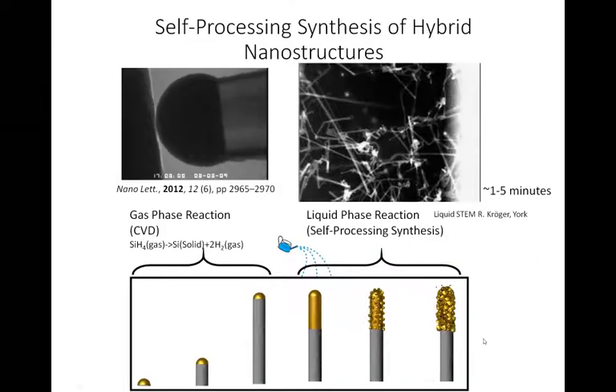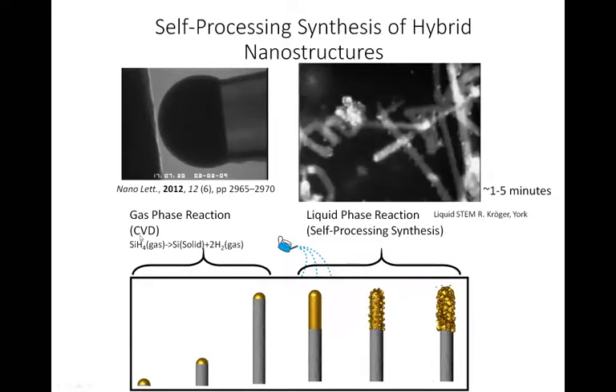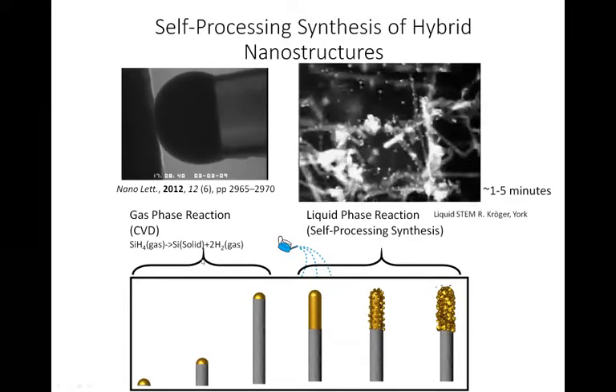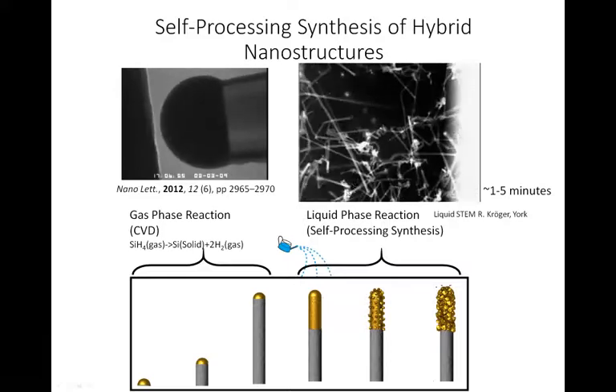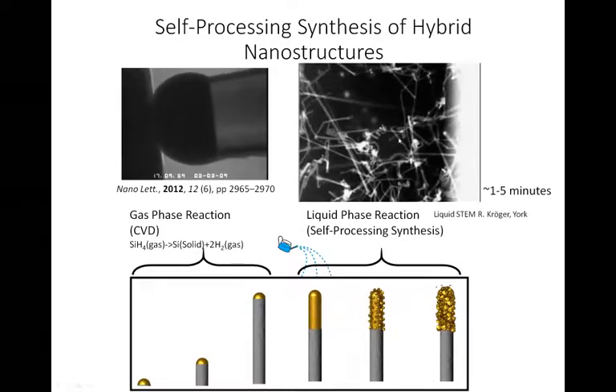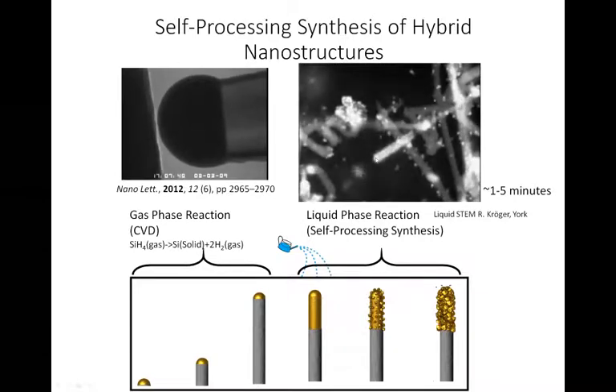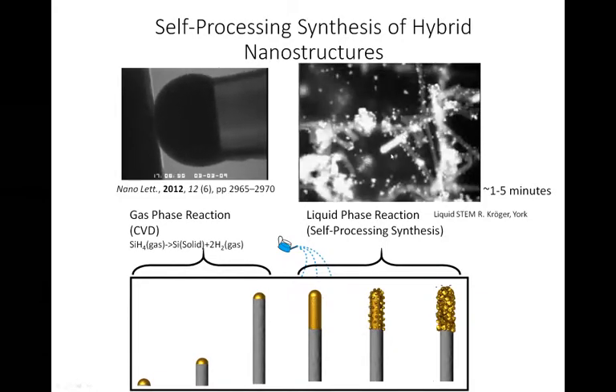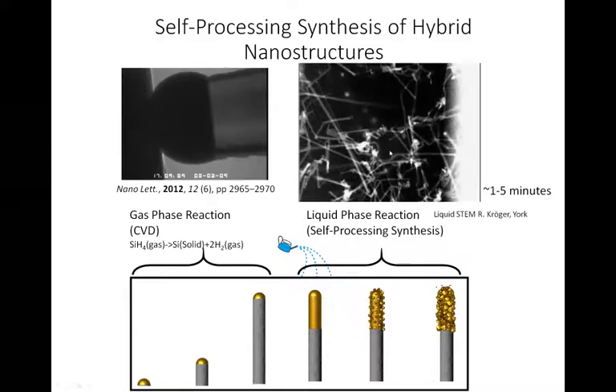So this is how it looks. We have the CVD synthesis of the silicon germanium alloy nanowire in the gas phase, and then in the liquid phase there is the deposition of the tip, as you can see here. This is in situ real-time STEM measurements showing the tip deposition of the Nano-Floret.